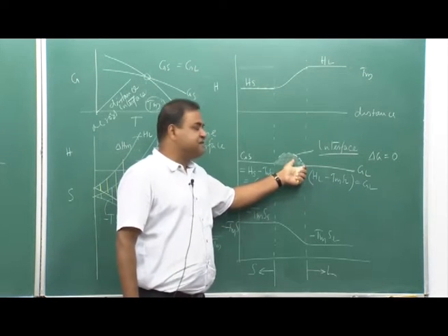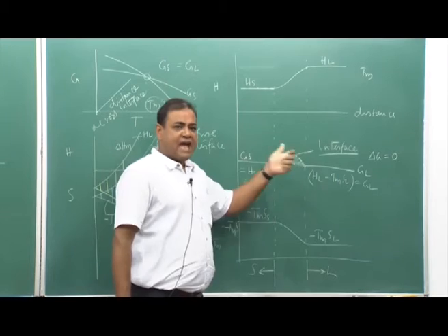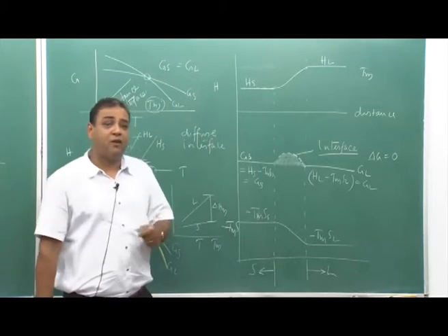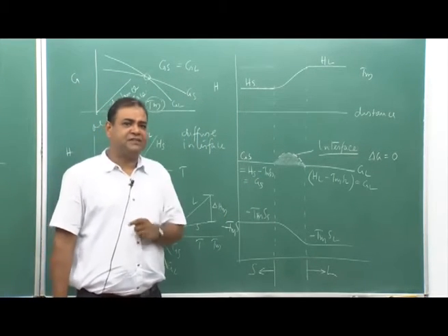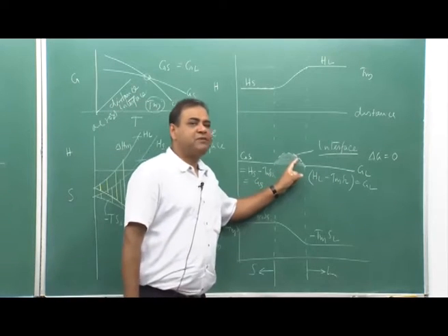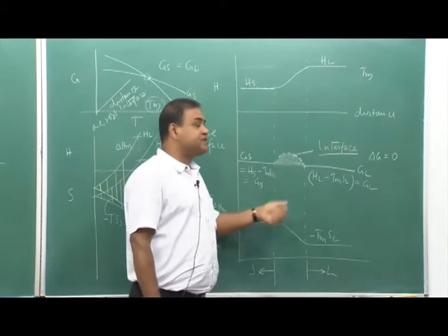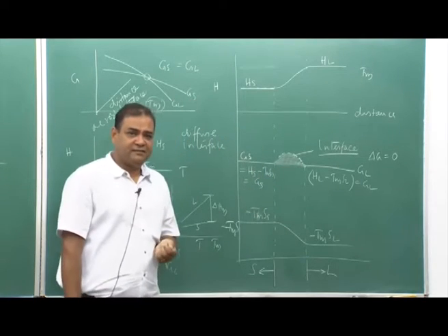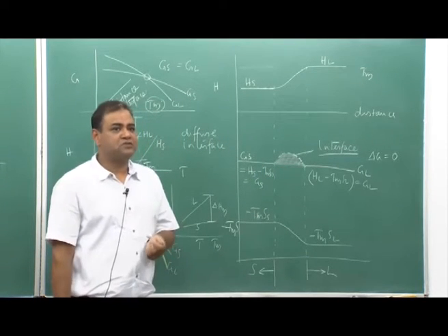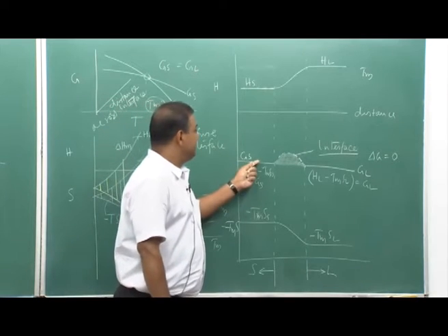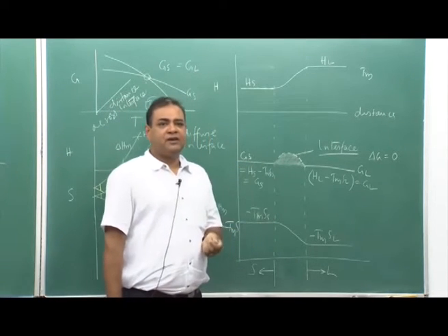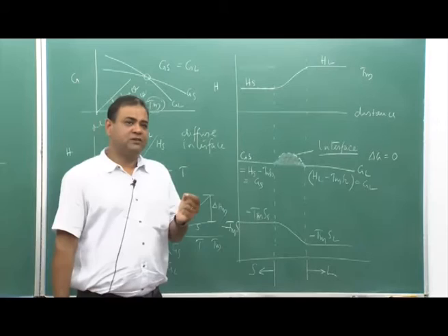And if there is a positive contribution and some solid forms, it cannot remain there because it is an unstable formation. It is not possible because there is an increase in free energy. So, the transformation is not possible. That means at the melting point no nuclei are possible.